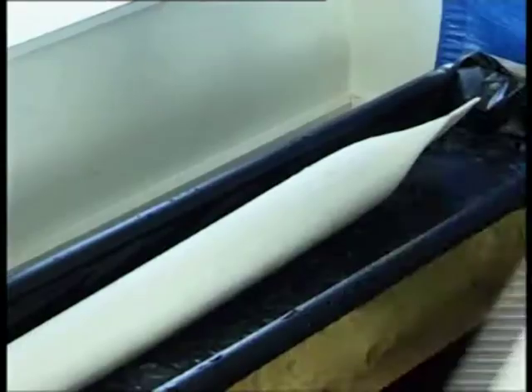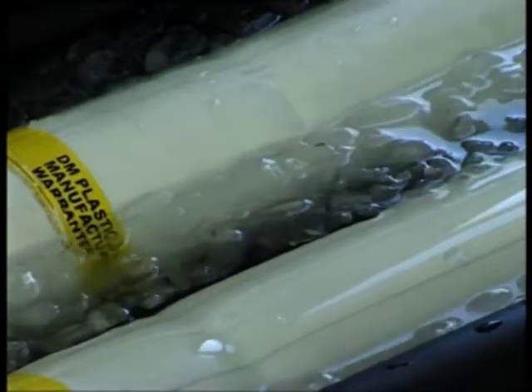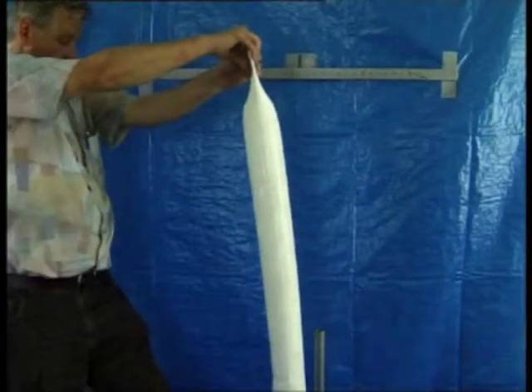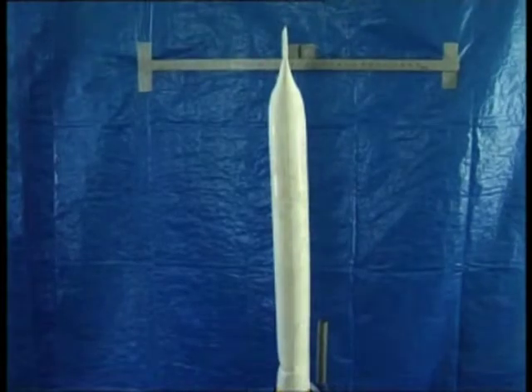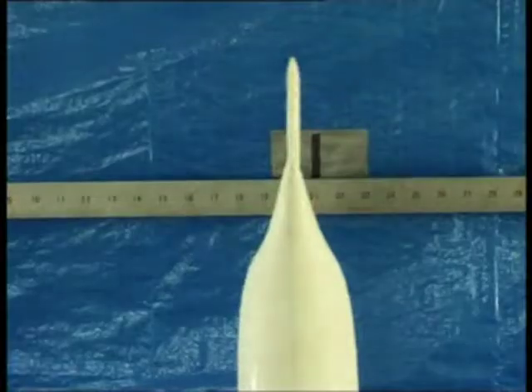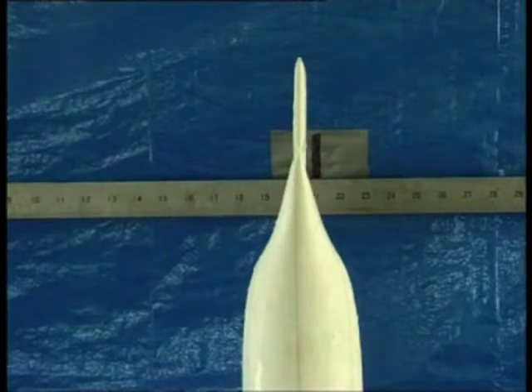The post was removed from the clamp and returned to the bath for reconditioning for 60 seconds. On the 4th procedure, the post was allowed to return to its normal position. The standard states deflection not more than 50 millimeters after 60 seconds. The PolySafe post achieved this, easily returning to the required standard.